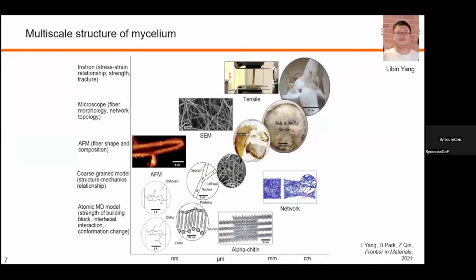And one of my students, Libin Yang, who's my first PhD student, started to focus on this study. We first built a multi-scale picture of this mycelium. We asked, what's the material composition of the fiber? Once the fibers come together, what's the connectivity between those fibers that defines the network? And then at larger scale, once you have a network, how fast can they grow? And once you take the mycelium from the petri dish and put it together with the biomass, how can they improve the properties of these biocomposites later?